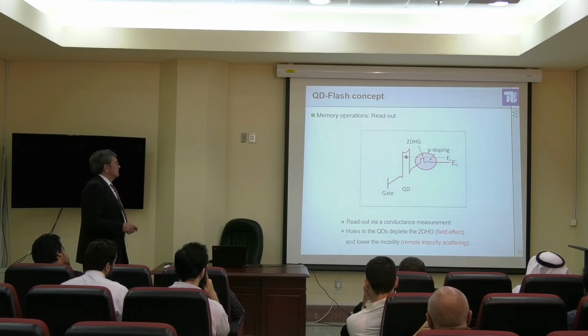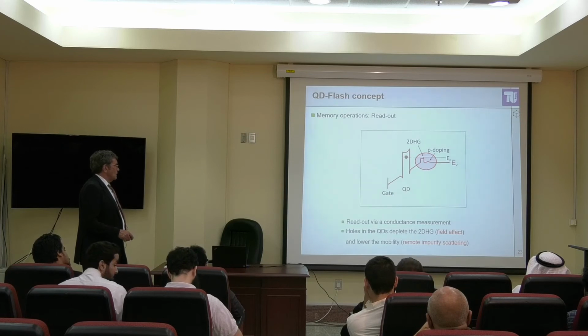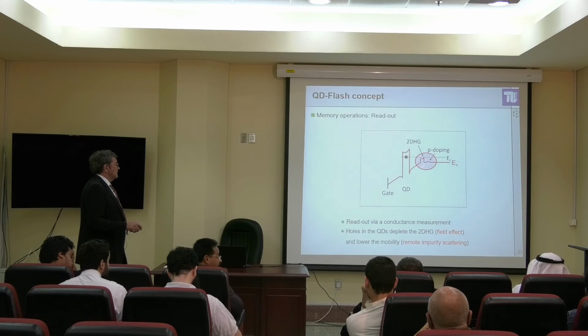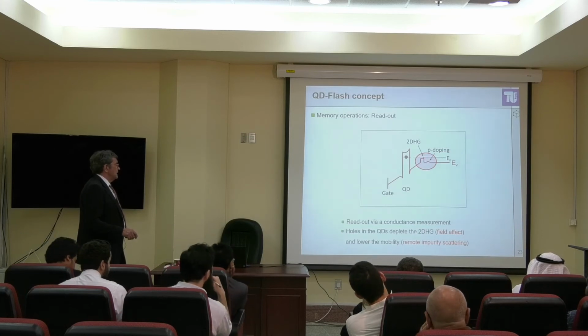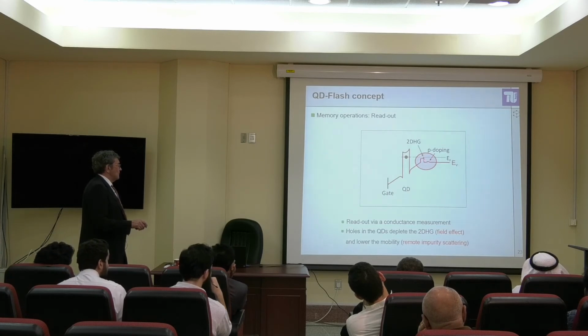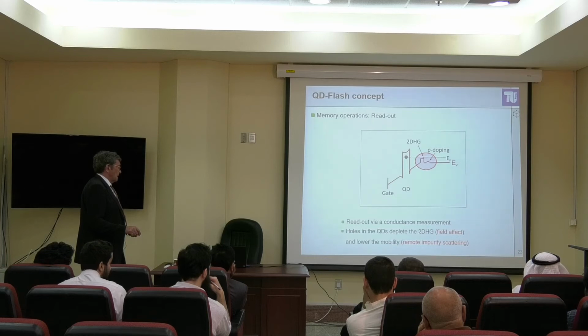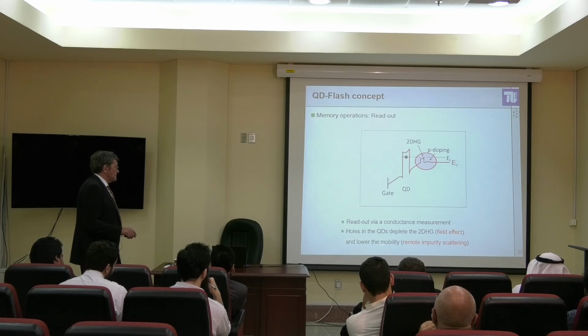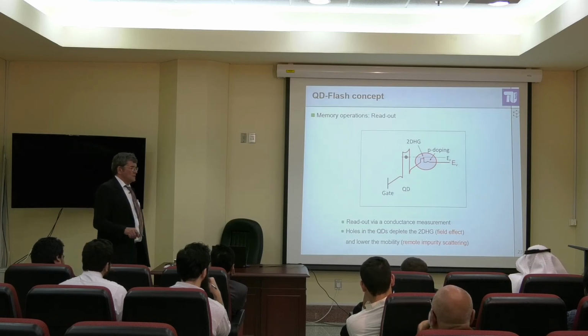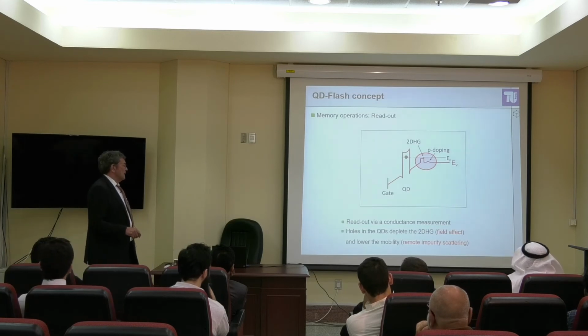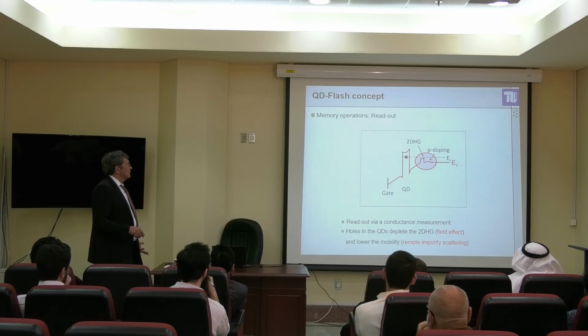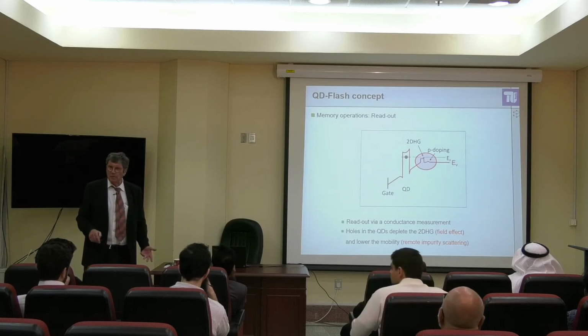Readout: you do some p-type doping. Readout is done via conduction measurement here. Holes in the quantum dot deplete the two-dimensional hole gas, which you generate by p-type doping. You deplete the hole gas by the holes in the quantum dots, and that also lowers the mobility, and then you have remote impurity scattering. That is actually the way to control which of the memory units are populated.